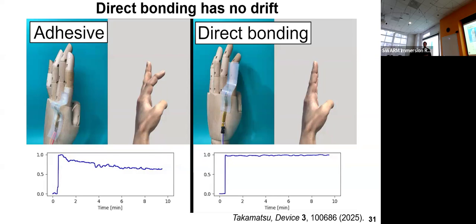Yeah. That is cool. Okay, and then does the thickness of the substrate affect how good the bond is? I think the thickness affects the bonding properties. But I'm sorry, we haven't tested the thickness dependencies yet. So maybe 10 micron should be okay. For our cases, 1 or 2 micron polyimide substrates are used, and the silicon is 5 micron. These thickness ranges are okay. 10 micron should be okay, but over 10 micron, maybe the bonding strength will decrease.